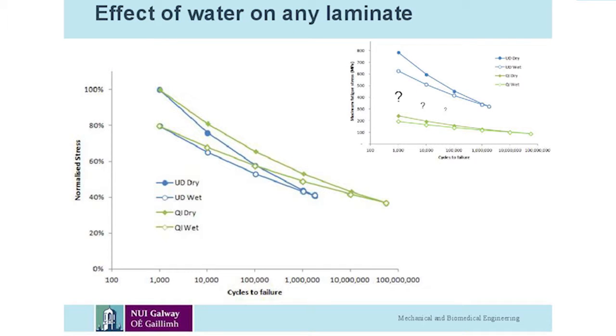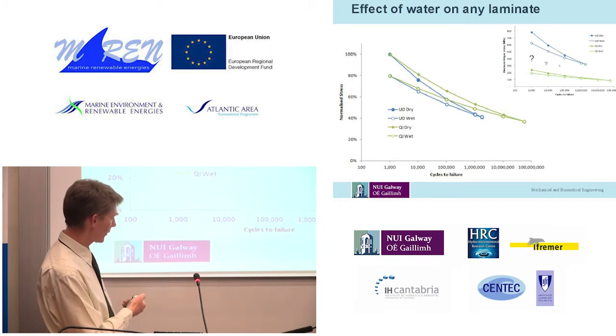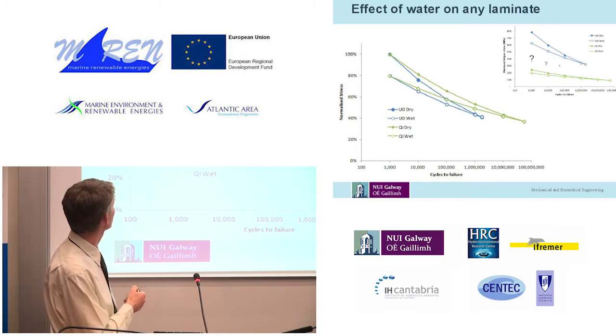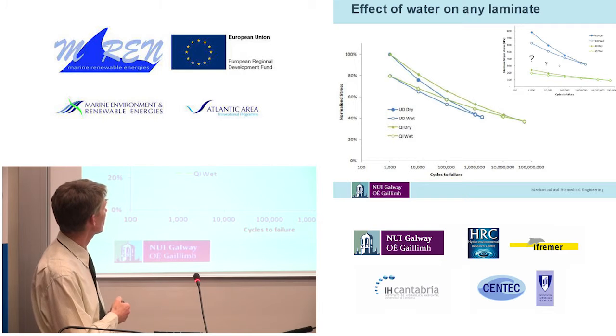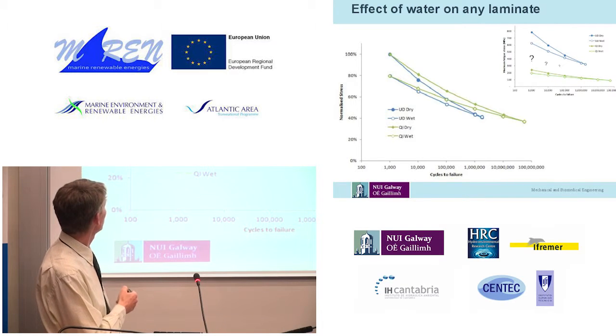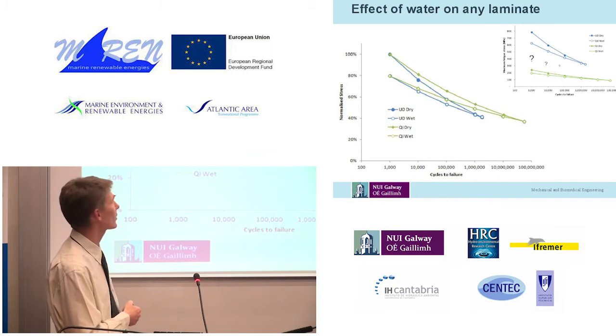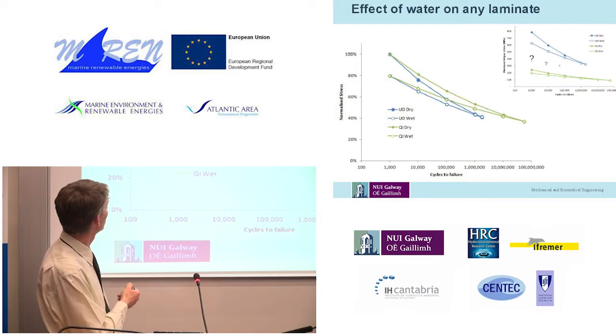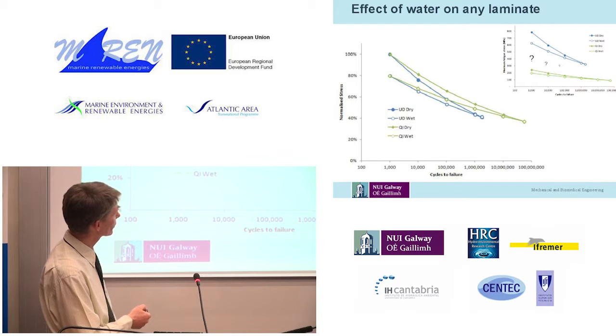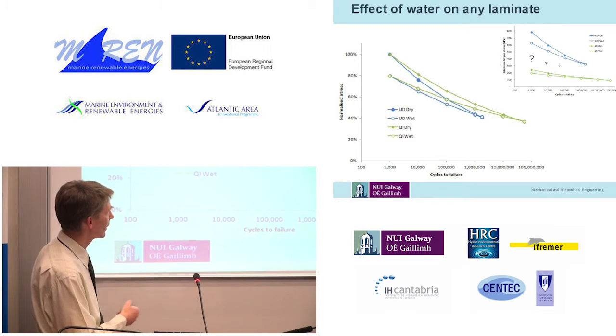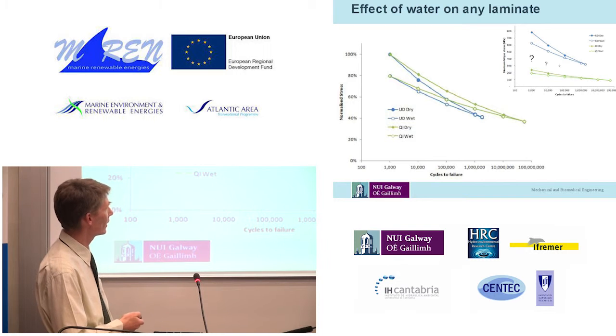So what I did was I've taken that data and I've normalized it by the dry fatigue strength at 1,000 cycles, and you can see that it comes out with a very nice pattern here, where at the high stress end of the curve, both the unidirectional material and the quasi-isotropic material essentially lose 20% of their fatigue strength when they're water saturated, and then that loss in strength is reduced steadily until somewhere between 2 million and 50 million cycles. The difference between the wet and dry completely disappears.